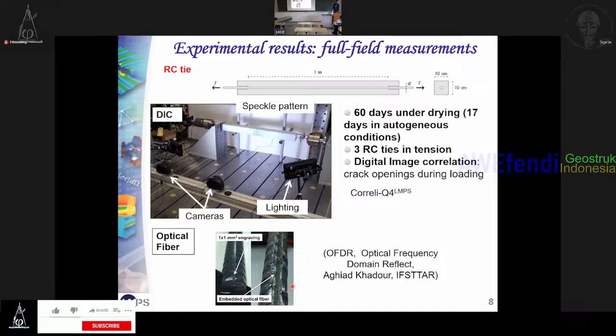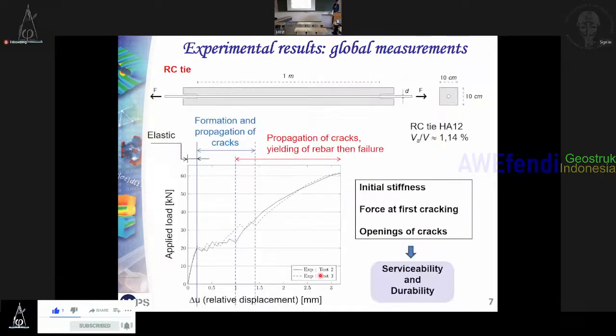For the optical fiber, we use optical frequency domain reflectometry techniques, which allow us to obtain the evolution of strain along the rebar with a resolution of a few millimeters. The device was developed by Agiat Kadour at IFSTTAR, which is now University Gustave Eiffel.